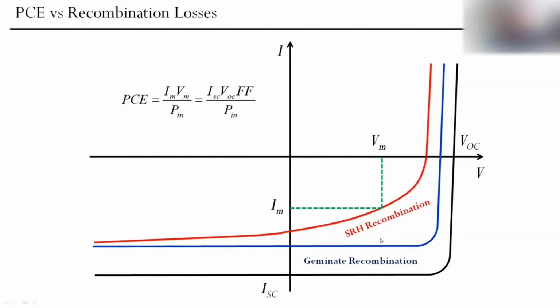Then if we add on top Shockley-Read-Hall recombination or trap-assisted recombination, we further reduce concentration of charge carriers, because keep in mind that for all these cases, we generate the same amount of free charge carriers.